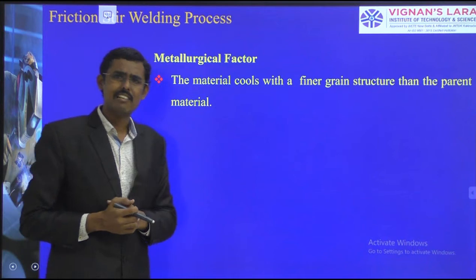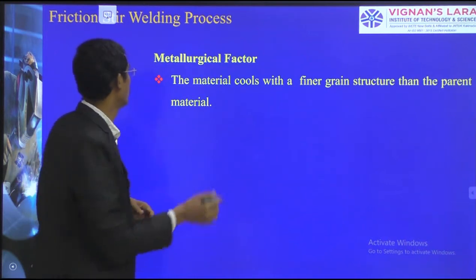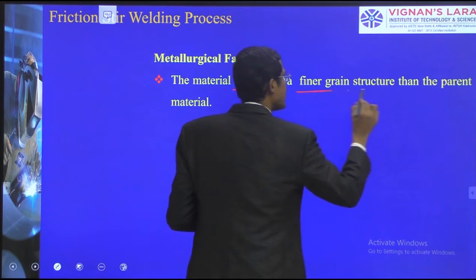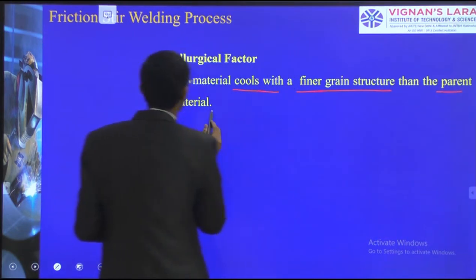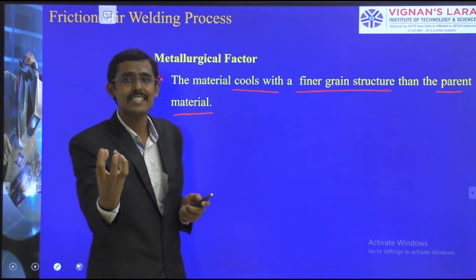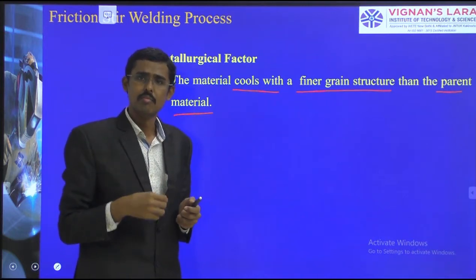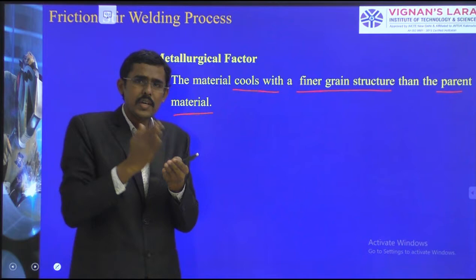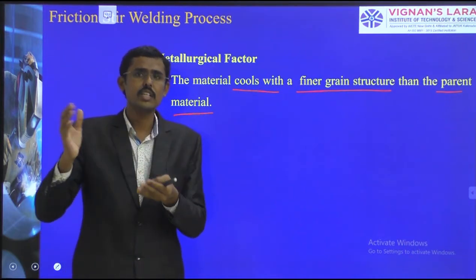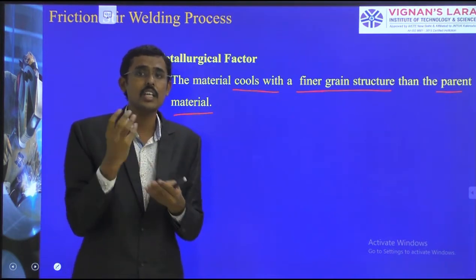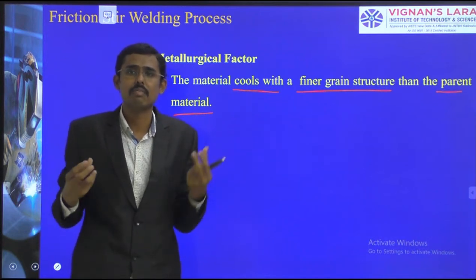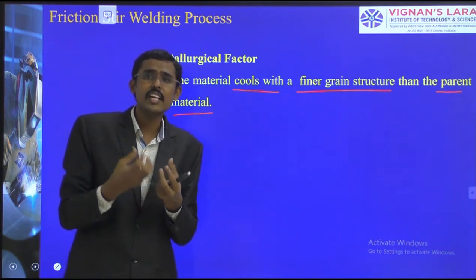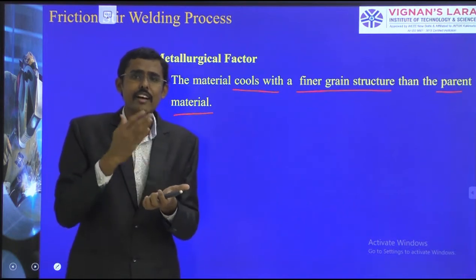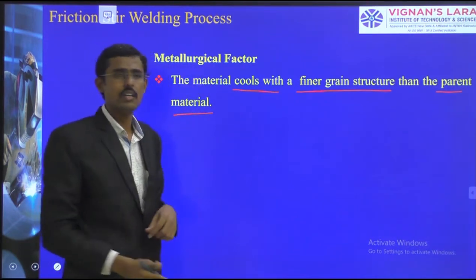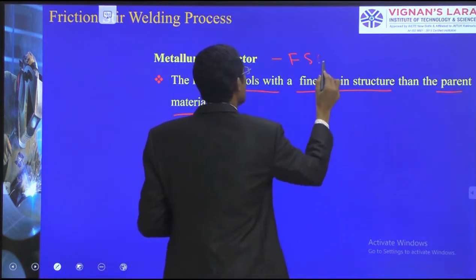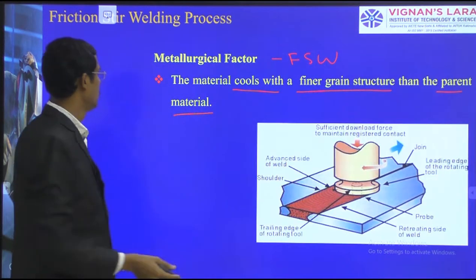What is the metallurgical factor here? The finer grains. We have already told you. The material cools with a finer grain structure than the parent material, because we are not allowing it to solidify as it is, because we keep on stirring. This stirring action splits and breaks the grains. If the breaking action happens, it is equiaxed. It is not developed by metallurgical solidification. So we achieve these equiaxed finer grains in the friction stir welding method.